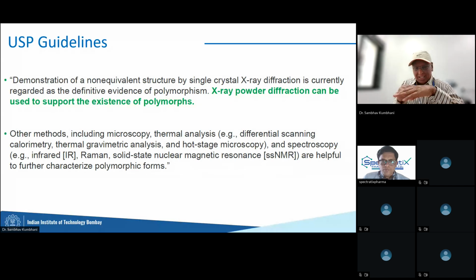So you have to slice. Although we say XRD is a non-destructive technique, nothing happens to your sample. But if your sample is not homogeneous, so you have layers of things, a few nanometer thickness layer of something, and then something else below it, and they are not mixing, they are not becoming one, no matter what you do. Sometimes it is knowingly done. You have coated something, multiple layers of coatings. You don't want to mix them. You want to let them be separate.